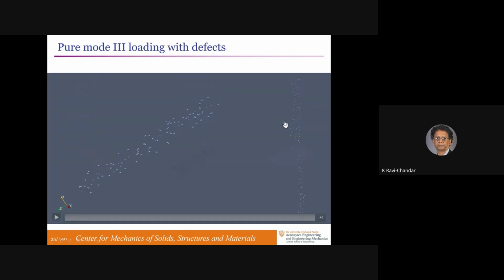So what do we do? We decided to implement the idea that defects are the key. So we introduced defects into our mesh. How do we introduce defects? You pick a cylindrical volume along the crack front and identify randomly about, I think it was 0.6% of the mesh points or elements, and provide them with damage, meaning that they're completely damaged, C equal to 1. And the rest of the things are intact. So this is now an initial defect field that has been prescribed over this volume, and we let them be subjected to the mode 3 loading.